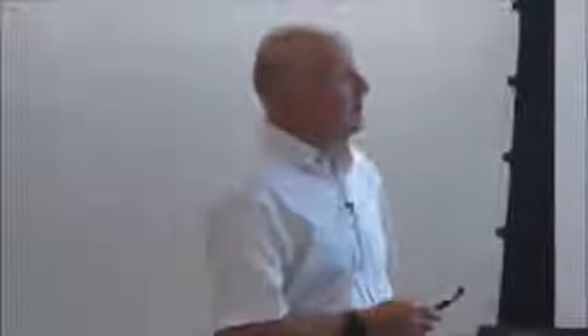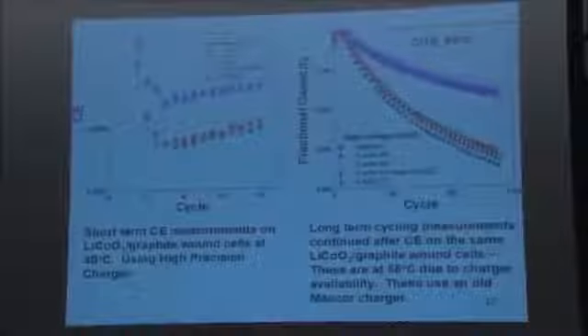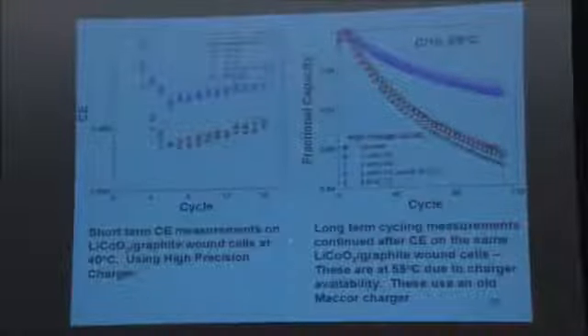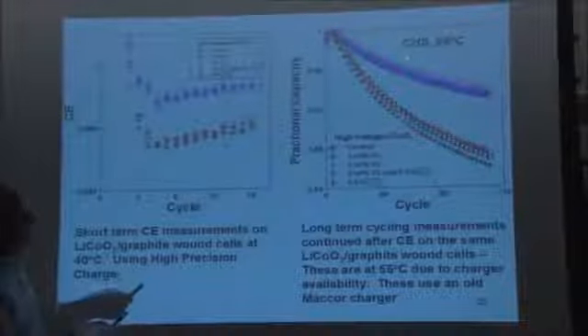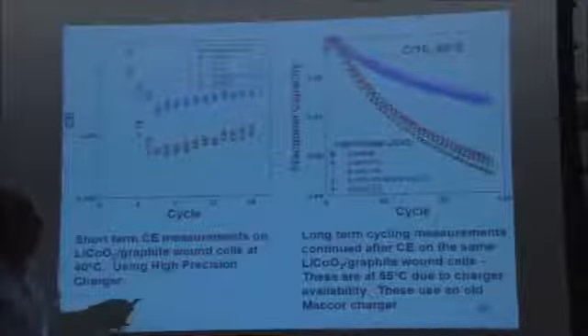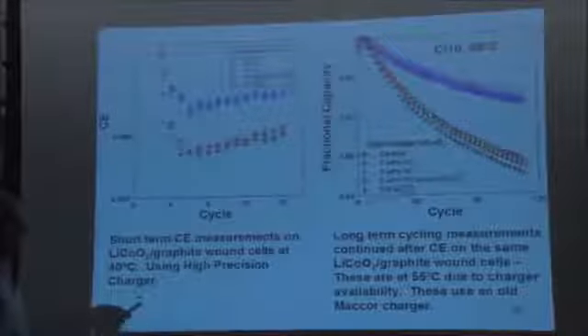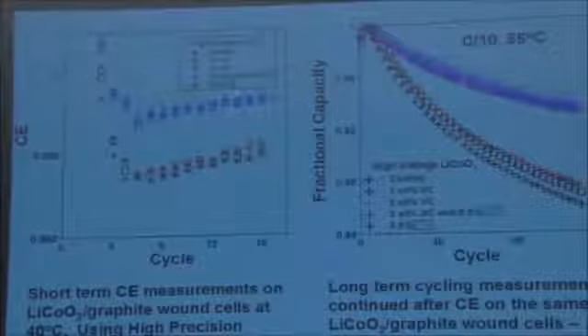So we've done this a few times where we take our short-term measurements collected over a period of a couple of weeks, and then we take the cells and we put them on a dumb charger and run them for long periods of time. So this is 20 hours for every cycle, 120 cycles, so 2,400 hours of testing. And we increased the temperature so that we could distinguish more quickly the differences between the cells. But you can see over here the cells that are best. This is a pale symbol at the top. I don't know what color it is because I'm colorblind. It could be anything, sort of gray or pink or something like that. It's pale. Anyway, it's the top one over here.